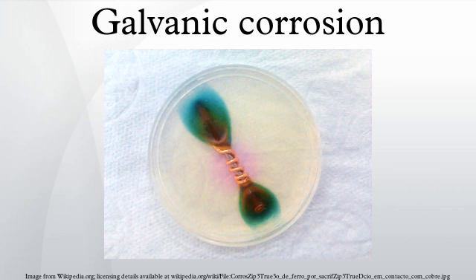Lasagne Cell: a lasagne cell is accidentally produced when salty, moist food such as lasagne is stored in a steel baking pan and covered with aluminium foil. After a few hours the foil develops small holes where it touches the lasagne, and the food surface becomes covered with small spots composed of corroded aluminium. In this example, the salty food is the electrolyte, the aluminium foil is the anode, and the steel pan is the cathode. If the aluminium foil only touches the electrolyte in small areas, the galvanic corrosion is concentrated, and corrosion can occur fairly rapidly.